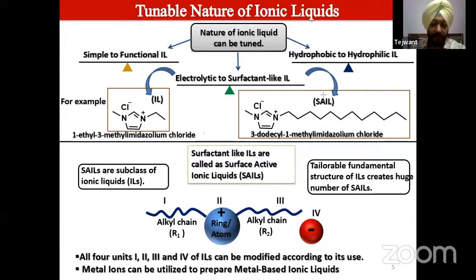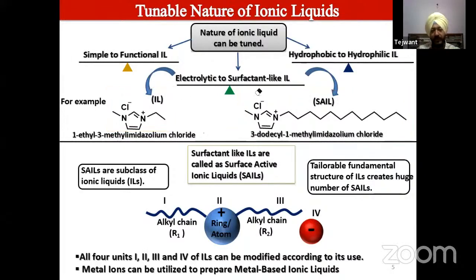So if we are talking about surfactants, such ionic liquids can lower the surface tension of water. They can be used as a template for the preparation of nanomaterials. They self-assemble, they form micelles, vesicles, or one can prepare microemulsions by using surface active ionic liquids. Further, this alkyl chain can be fine-tuned by putting some functionality there. We can tailor-make them. If we append the alkyl chain with an amide, ester, or some other functional group, we can modify the properties of the ionic liquid surfactants.